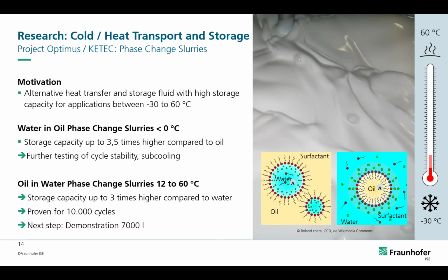One is the combination of water plus oil for phase change slurries below 0 degrees as a temperature range. So we have a storage capacity that's 3.5 times higher compared to if we would use pure oil. Here we do not have too much long duration tests, so we need to further investigate the cycle stability and the subcooling effect of the systems.